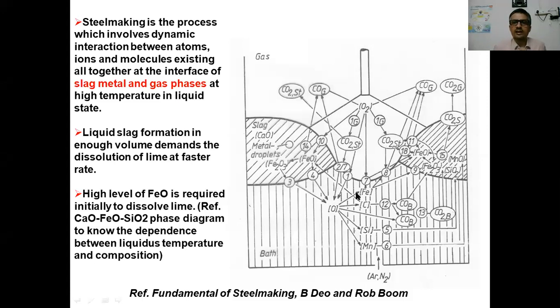So basically here the thermodynamics is going to operate. As per the thermodynamic driving force, oxygen is going to react with silicon first, followed by other elements like manganese, then carbon, and so on and so forth.